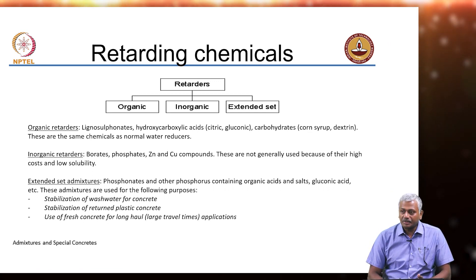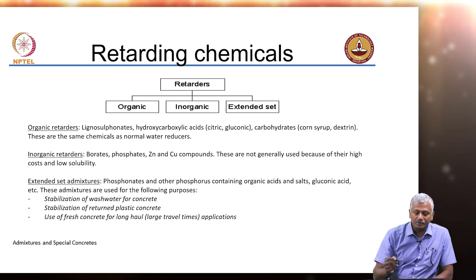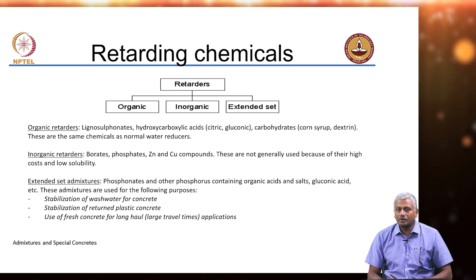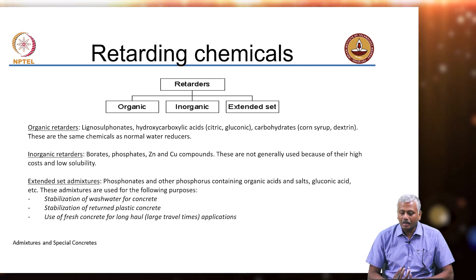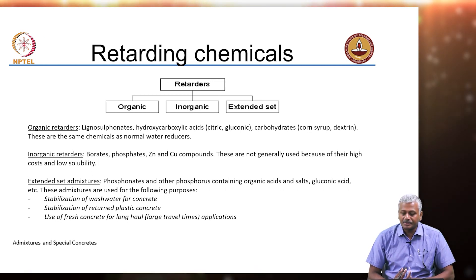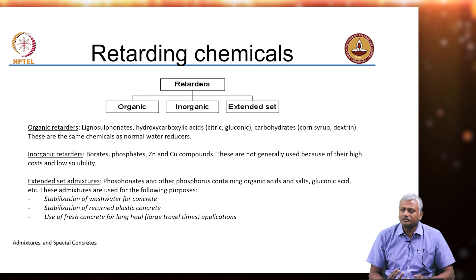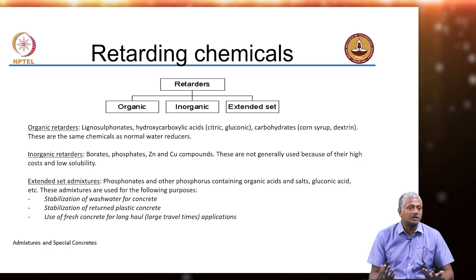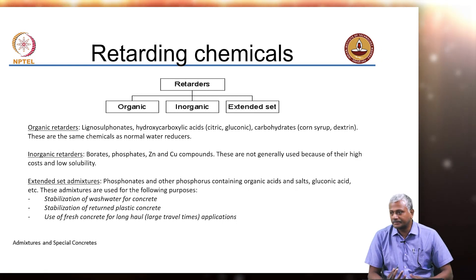Retarders are typically classified as organic or inorganic. Organic retarders include the same chemicals used as normal water reducers: lignosulfonate, hydroxycarboxylic acid, and carbohydrates. These are all regular retarders and fairly inexpensive — for instance, sugar or corn syrup are all excellent retarders.